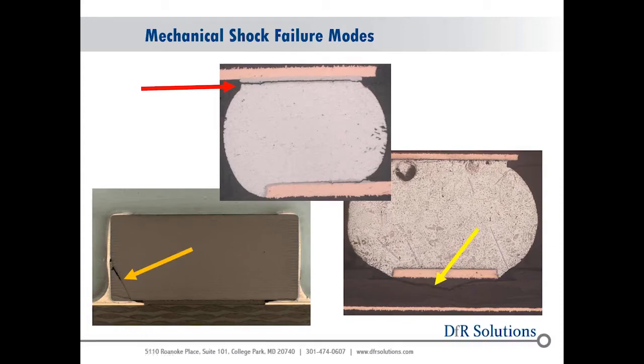In this case, it looks like we have a nickel layer up here, and a copper intermetallic down here. So this would be a tin-nickel intermetallic on the top, a tin-copper intermetallic on the bottom. The intermetallics themselves are fairly stiff, high modulus with respect to the solder, and very brittle. So under an overstress condition, they're not going to plastically deform. You're going to get a brittle crack, and it's just going to propagate very quickly through that interface.